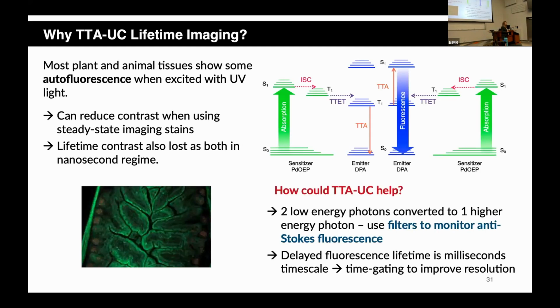So how can TTAUC help? Well, we know we're taking two low energy photons and converting them to a single photon of higher energy. So we can use filters and just look at this anti-Stokes emission rather than the normal lower energy fluorescence. So we're splitting off from the autofluorescence, but also it occurs on a completely different time scale. The absorption happens here, and we've got to go through all of these different photophysical processes, so the end photon comes out on the millisecond time scale compared to normal fluorescence, which would be on the nanosecond. So you can use temporal gating to split the emission off.